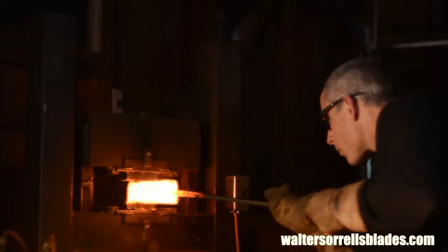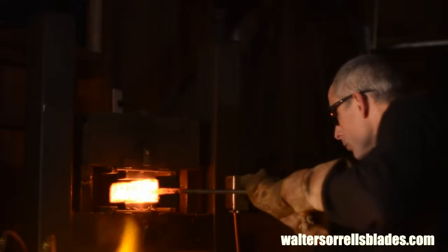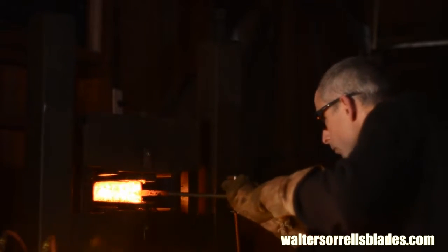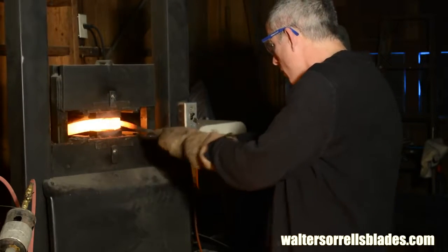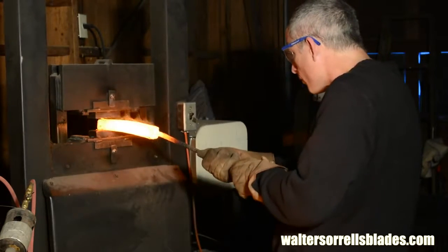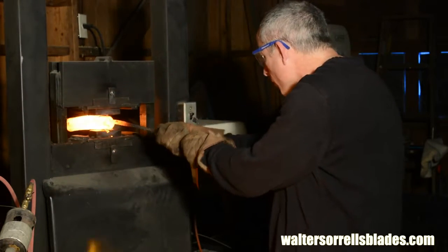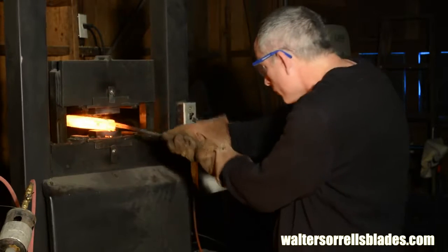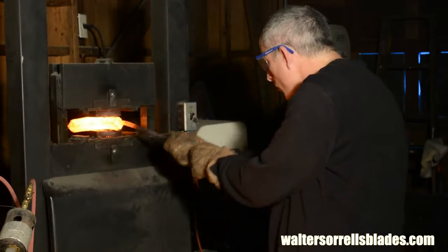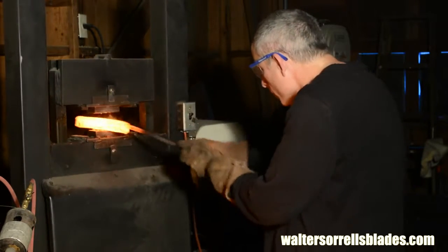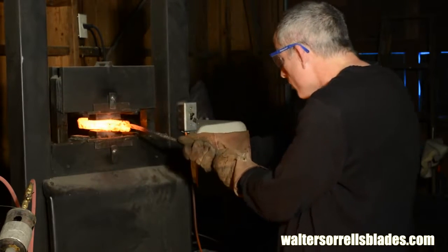Next, I'll start drawing out my billet. As you flatten it, if there's even the slightest play in your dies, it'll tend to slip sideways a little bit, forming a kind of diamond cross section. Before that happens, you'll want to fix it. Just turn it 45 degrees and push the whole thing back to true. Once it's trued up, you can get back to squaring everything.